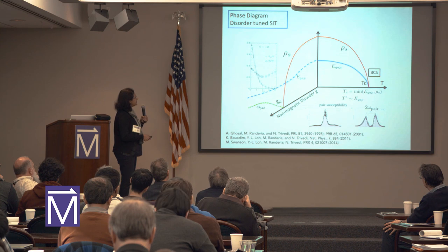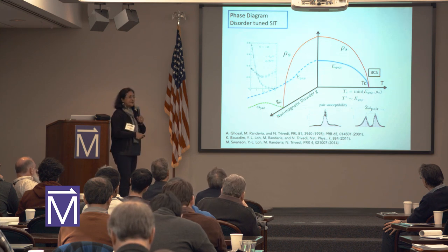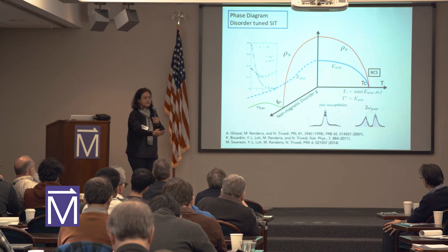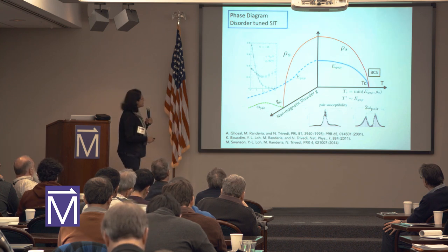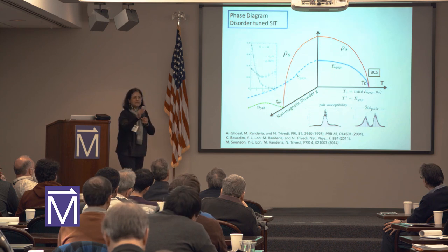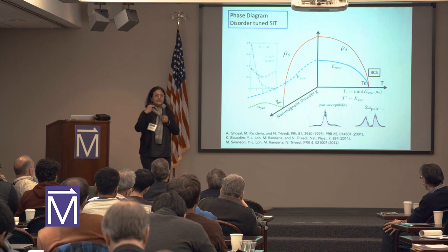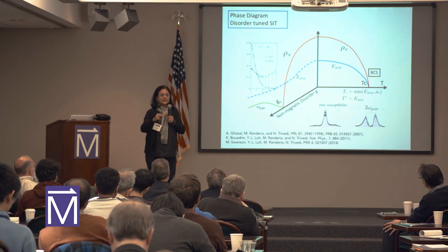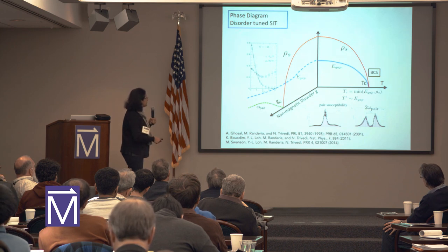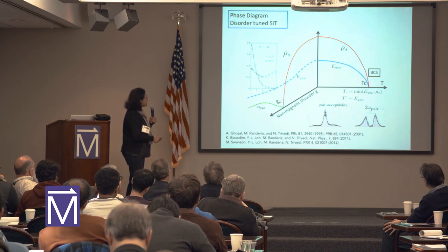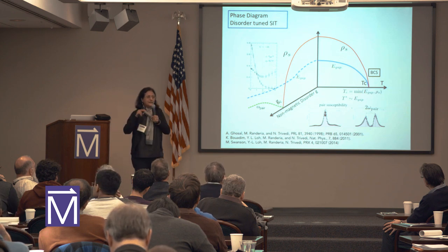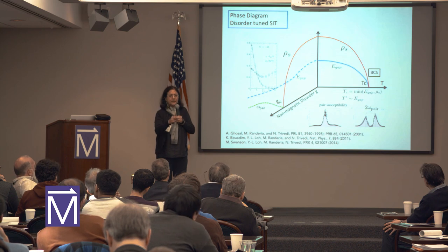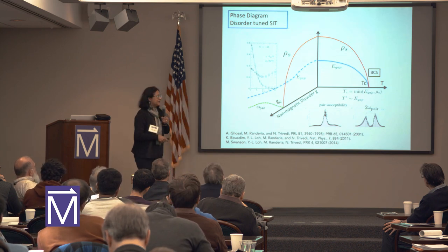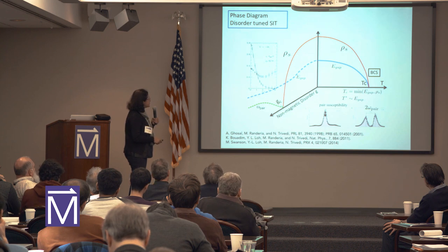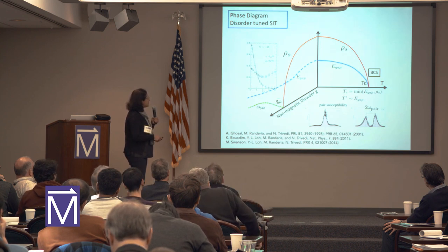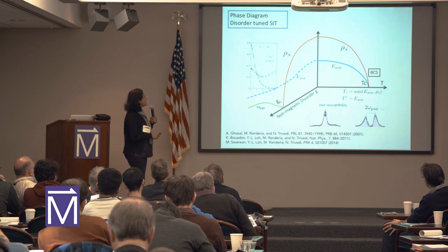And this critical point, now on the insulating side, has pairs, but it goes soft by another energy scale, and that is the Josephson scale. So if you try to tunnel two particles into the insulator, there is a gap. In the superconductor, there is no gap to that, so that is zero here. So the Josephson scale is zero inside the superconductor. But in the insulator, there is a finite cost to tunneling a Cooper pair into the insulator, but that scale also goes soft at the transition. So this is the way we can describe this quantum phase transition in the S-wave superconductor.